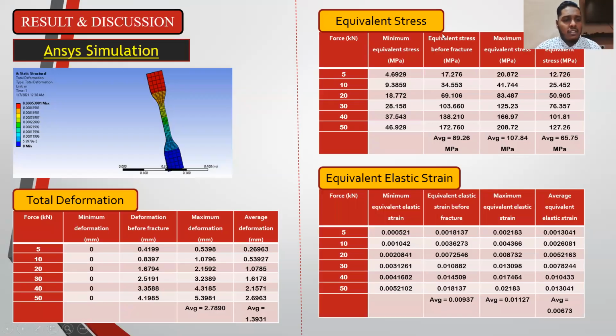And for the result and discussion on the ansys simulation, we tested using the dog bone shape, and the total deformation is obtained, where we can see the deformation before the fracture. We can see it in the orange region of the figure, and it shows that when the force is high, the deformation is also high. For the equivalent stress, we set a few forces, starting from 5 kilonewton to 50 kilonewton. When the force is higher, the stress is also higher. The same goes for the equivalent elastic strain. And we calculated the average of the maximum equivalent stress and also the strain, and we plotted a graph of the stress and strain curve, and we obtained that it is directly proportional.